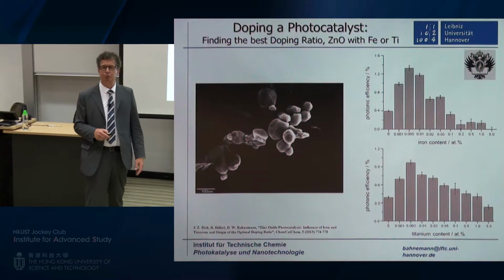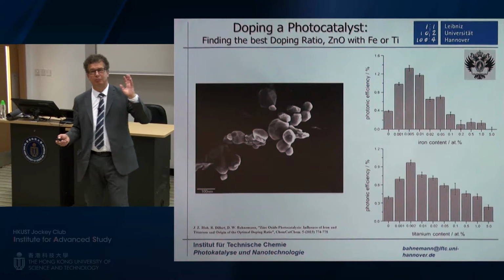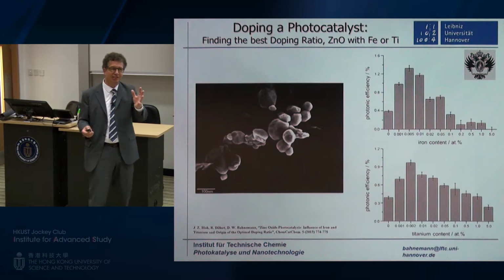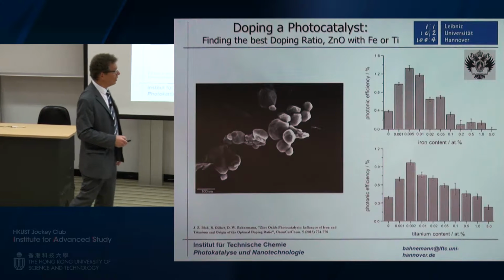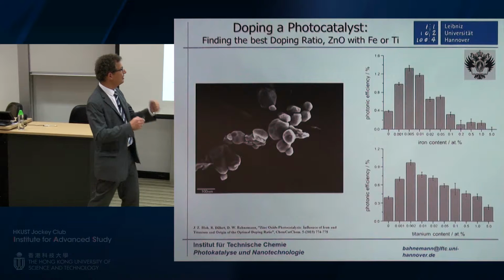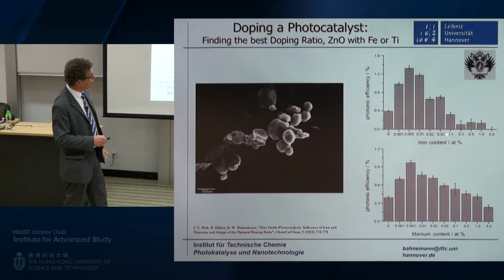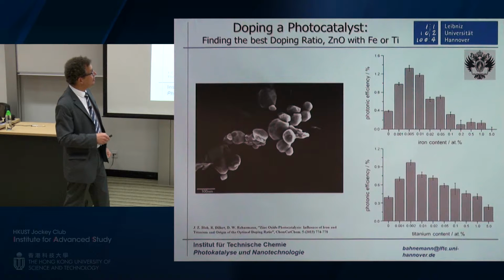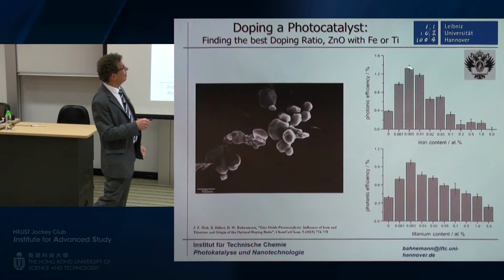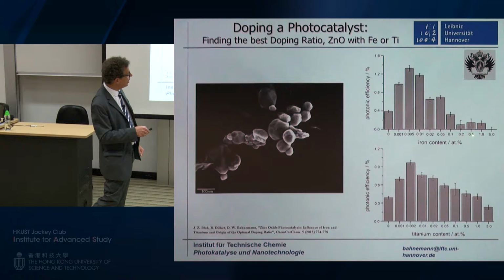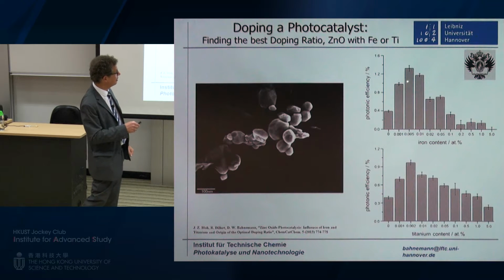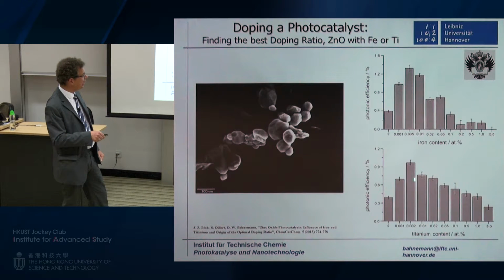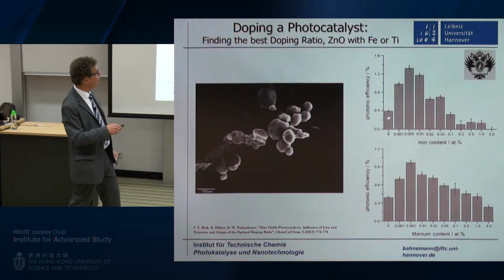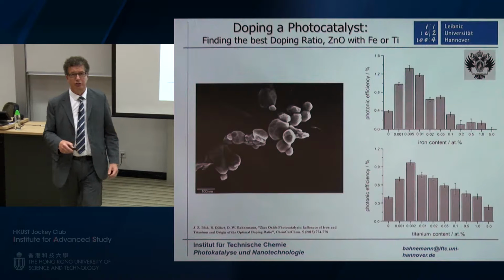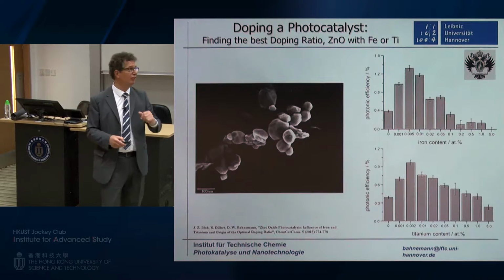Why would he choose 0.5 atom percent? Because everybody in the literature says the magic number, 0.5 atom percent, is the amount you should put in as a dopant. Well, but he was at the beginning of his thesis and he said, no, I continue. And so he put smaller and smaller amounts of iron and titanium in the system, and his work was rewarded by finding materials which now do not contain 0.5% but 0.005%, or even here 0.002% of titanium, and they showed significantly higher activity, 3 times higher than pure zinc oxide. So doping is possible, but here at a much lower level.